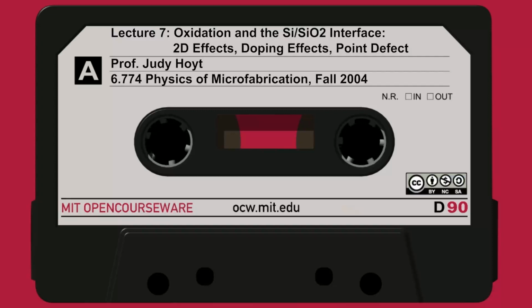And you can already see, even for a thin oxide, right immediately, some corner effects. The oxidation rate's a little slower here and here compared to on the flat. And on the far right, the corner effects are still evident, and I'm starting to develop this bird's beak thing. The stress of the nitride is causing the oxidation rate here to be also a little slower, and the fact that it has to diffuse through.